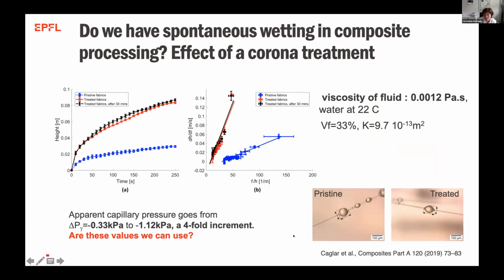We actually treated the fabric with the corona treatment. It's not coronavirus, and not the beer either, but this corona pen, which is a kind of atmospheric plasma, which really activates the surface and increases the wetting of the surface. We see it in the contact angle: the pristine fibers that we extracted from the fabric have a pretty large contact angle. On the treated one, it's a bit smaller, so it wets better. And if you look at the height versus time, in the pristine fabric you go like this, and in the treated fabric you go much higher.